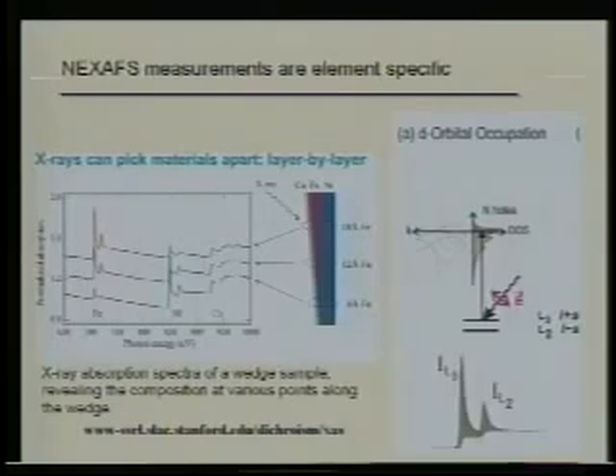This is really nice because from your wedge sample, you can strip off the layers one by one. Now, another thing to note here is the actual intensity, or how large these peaks are, scales with the number of empty states that the electron can transition into. So we see iron has the most empty d electrons, and we see that that peak actually is the strongest. Whereas copper, you see it's actually quite weak. It doesn't have those very sharp d lines, sometimes called the white lines. And that's because copper is d10.